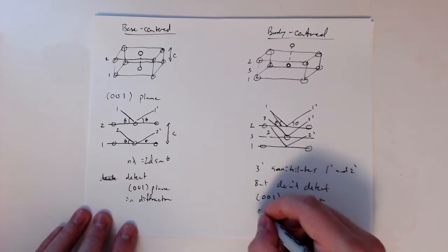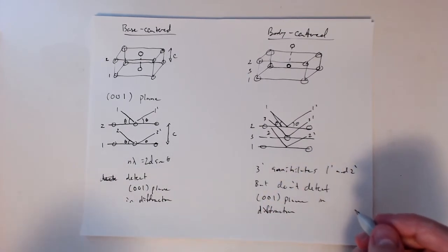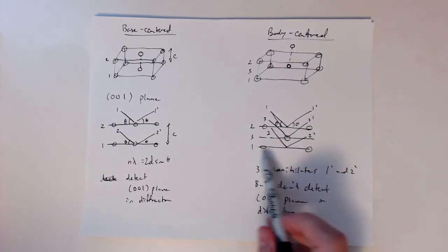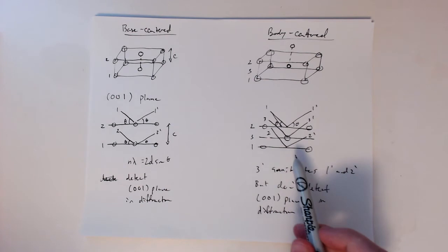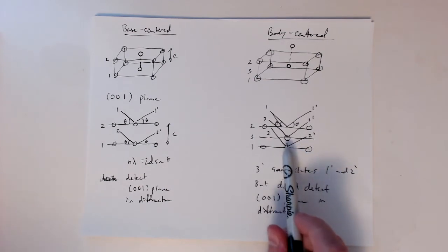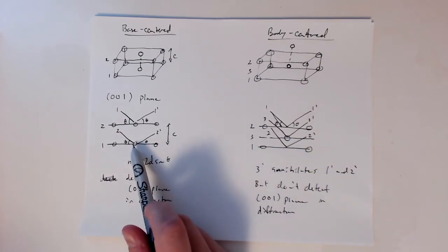So we don't see that in diffraction. So this means that regardless of what we do, we shouldn't expect to see the 001. It's not to say that the 001 plane doesn't exist. You know, we know it's there, right? We can always draw a 001 plane. But the way the diffraction works is it's being canceled out by the extra atom in the middle, whereas this one had the extra atoms in the plane, the 001 plane.